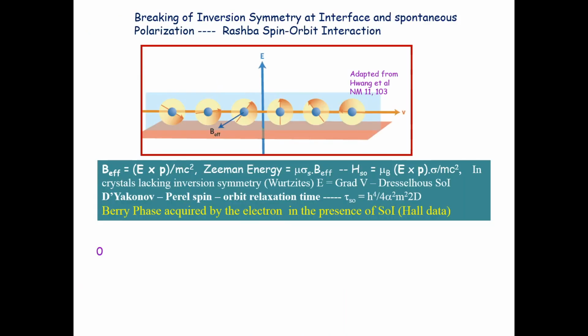One remarkable effect of creating an interface is that you break inversion symmetry across it. Because of the broken inversion symmetry, you have a built-in electric field normal to the interface. Now if I consider the diffusive motion of electrons at the interface, then in the frame of reference of this electron, the electric field actually appears as a magnetic field. The effective magnetic field seen by the electron is momentum dependent, it's written over here. And this electron will have an interaction energy with this effective magnetic field, that is your Zeeman energy. I can write down the Hamiltonian in this form, momentum dependent, and that is what is called the Rashba spin orbit interaction Hamiltonian. I am considering nearly free electrons, so this is linear in momentum.